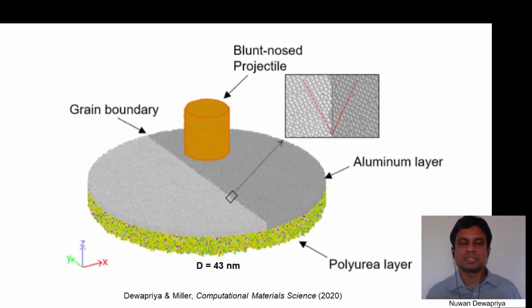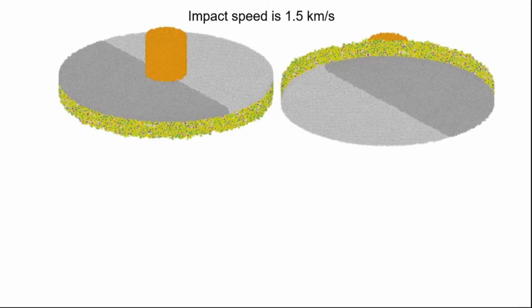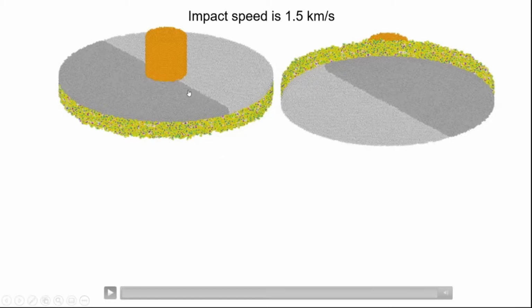So, we use MD simulations to simulate impact test of multilayer polyurea aluminum films. The aluminum films have a grain boundary in the middle and the diameter of the sample is 43 nanometers. Aluminum and polyurea have similar areal densities. I am going to show you a movie of the MD simulated impact test of these two structures. In this structure, aluminum is on the strike face. In this structure, polyurea is on the strike face.